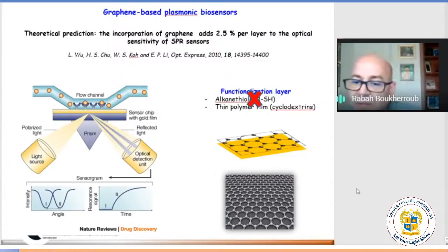So the reason why we wanted to replace these functionalization layers with just a single or 2 layers graphene, there was a paper that came out in 2010, just a theory saying, well, if you have a graphene layer on the gold surface, you should be able to improve significantly the sensitivity. So first we wanted to indeed check that, but also because graphene has a high surface area indeed and has really very different ways of functionalizing.